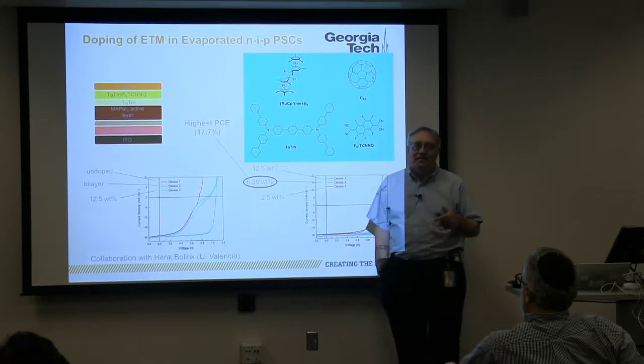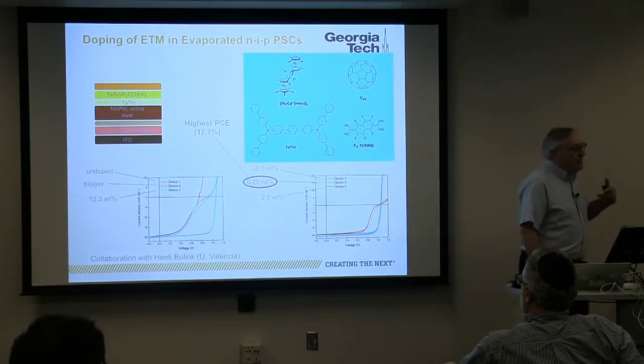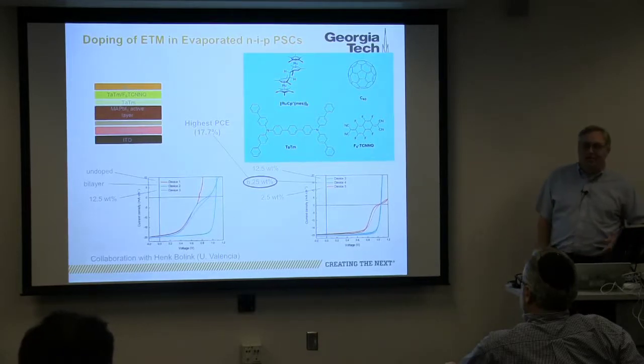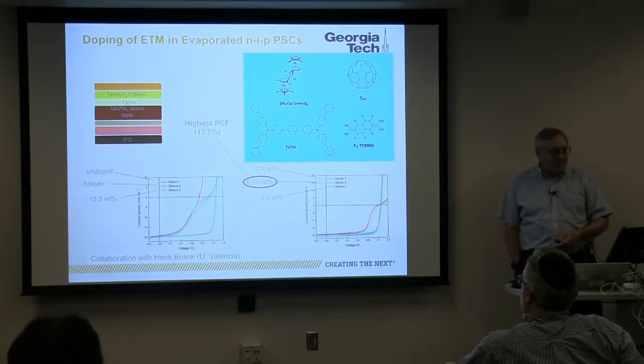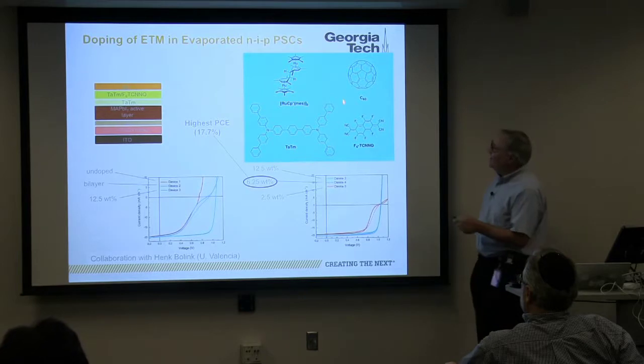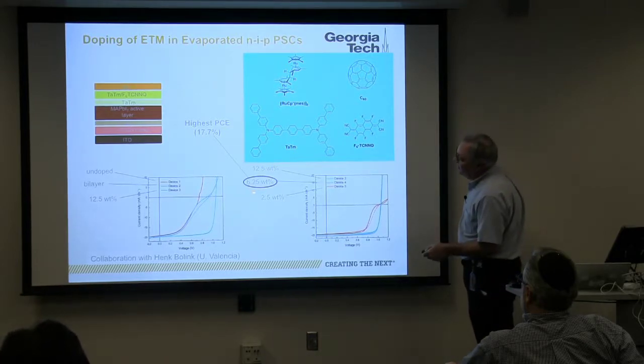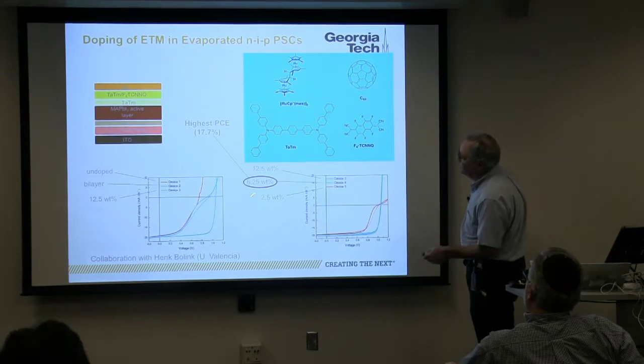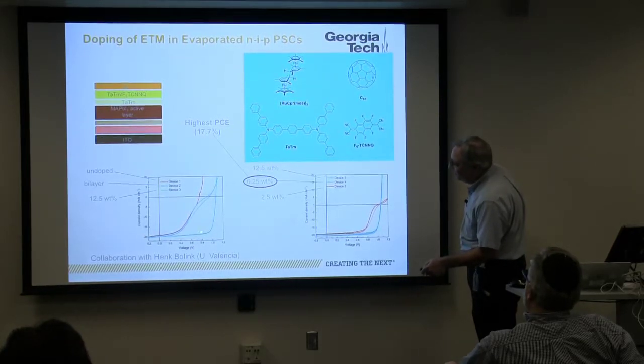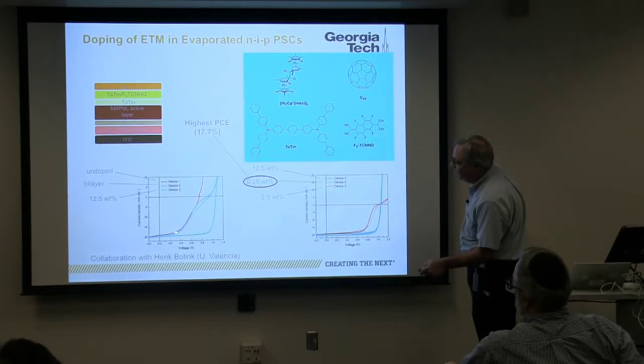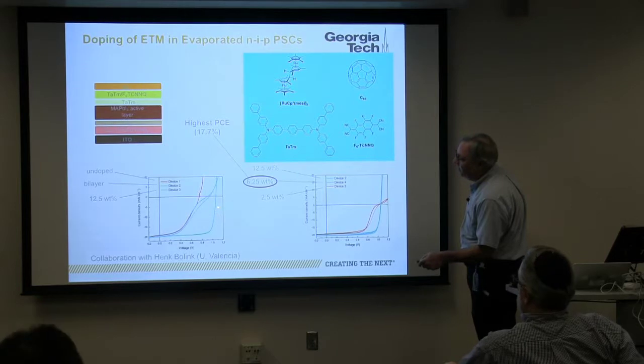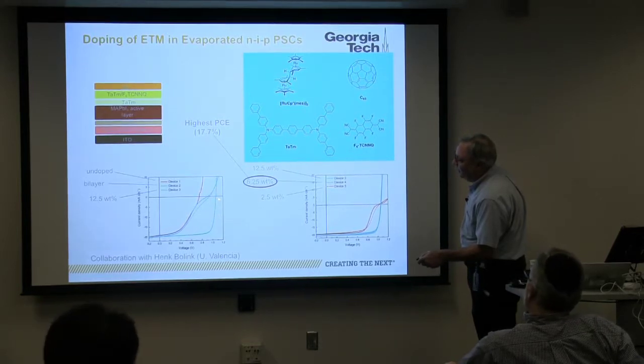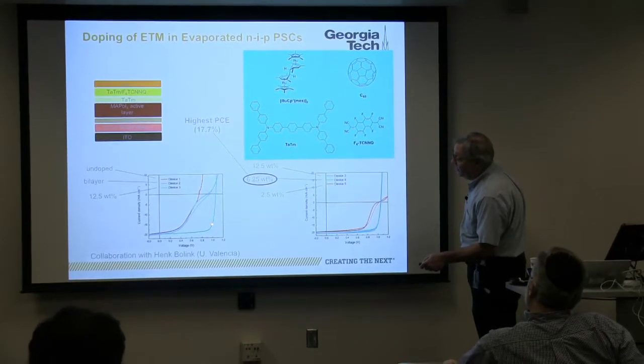curves. We're calling them S-shaped curves in the community, and that is indicative of a barrier to get the electrons out of the device. You put in just a tiny, tiny bit of, well, actually it's about 6 weight percent of this into this material. And you see here the curves, which are classic curves for a PV system. So we've basically killed the charge barrier for collection of the electrons.